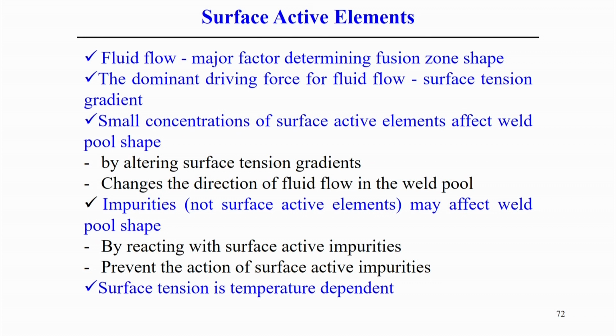So, that means we generally assume a stationary molten weld pool, but very intuitively if you look in depth at the analysis of the weld pool, the molten metal actually flows in a specified direction, and that flow is driven by different driving forces, mainly the surface tension force, which is mainly responsible for the liquid metal flow within the weld pool. And of course, indirectly that flow also affects the shape and size of the weld pool.